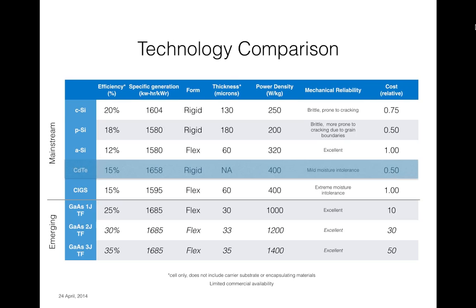And so generally, gallium arsenide materials will run cooler than their counterpart materials because they're much more efficient at converting light. And it's a meaningful amount. Normally a crystalline silicon solar cell sitting up in direct sunlight will reach about 45 or 50 degrees C. A gallium arsenide solar cell will run about 10 degrees cooler. And so there are certain applications where that becomes a very important factor.